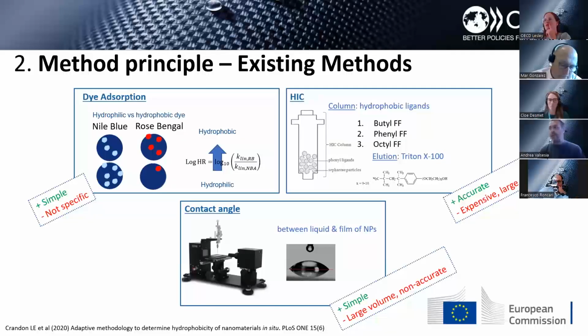For example, if you want to measure the hydrophobicity of a nanomedicine or a nanomaterial present at very, very small concentration. The third method is the contact angle method, which is the golden standard for measuring the hydrophobicity of flat surfaces. You leave a droplet of water on a surface, and with a goniometer, you measure the contact angle formed between the droplet of water and the surface. This is a very simple method, widely used to measure the hydrophobicity of flat surfaces.